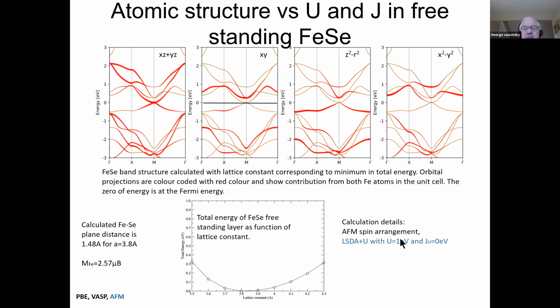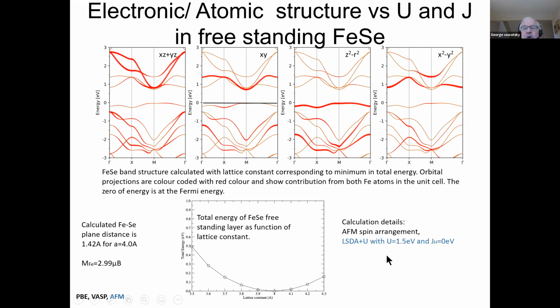And if you switch on a small U, 1 eV, it changes completely again. And if you switch on a U of 1.5 eV, it changes again completely and you have a huge gap. Remember, your Fermi energy here is always put at the top of the valence band, okay? So in DFT, that's the usual way of doing it. So the gap here is almost 1 electron volt. Okay. And you have this very flat band right at the Fermi level. And it has a very strong z squared character, not xy, not xz, yz, but z squared.